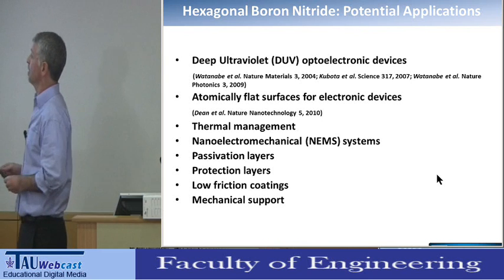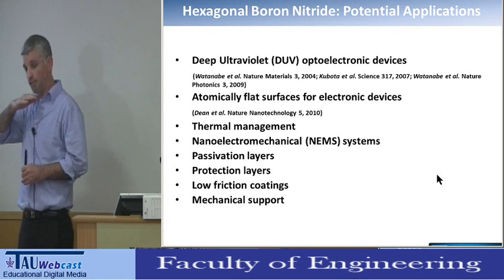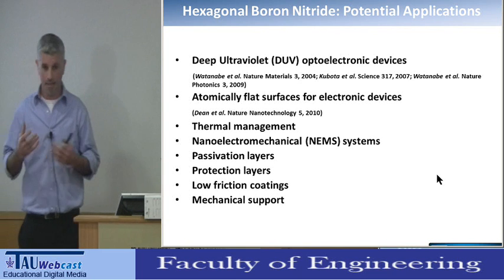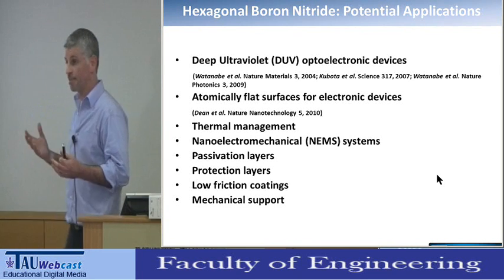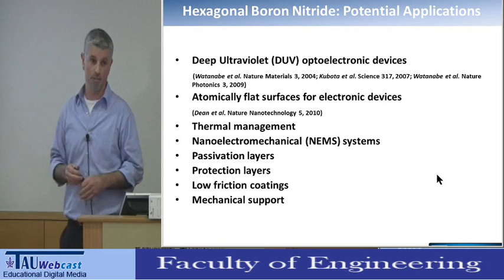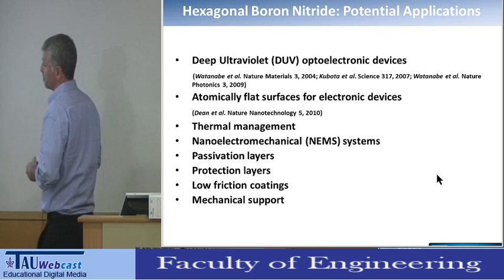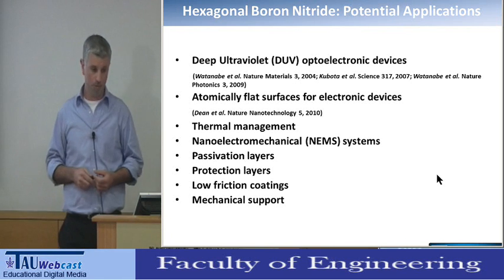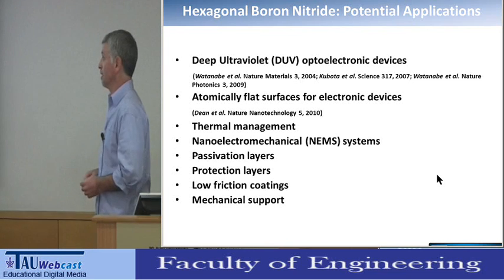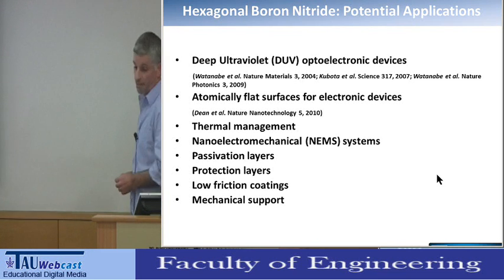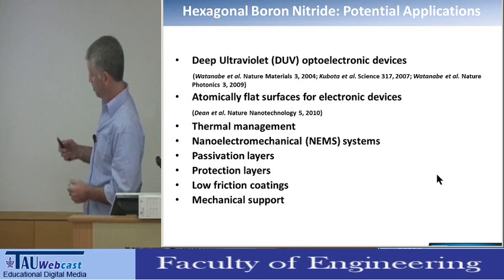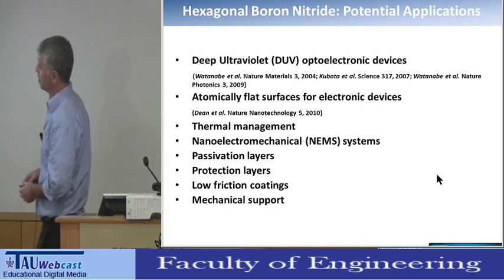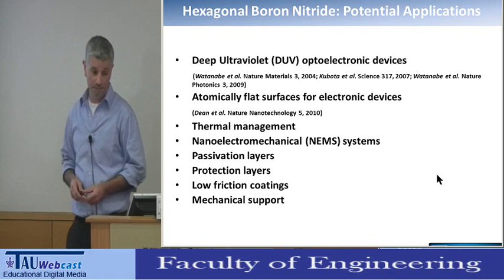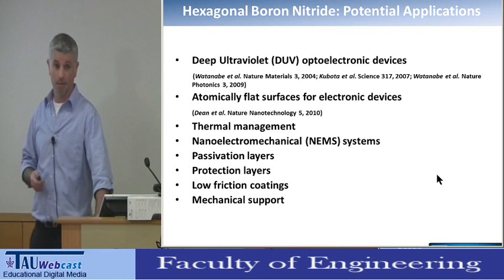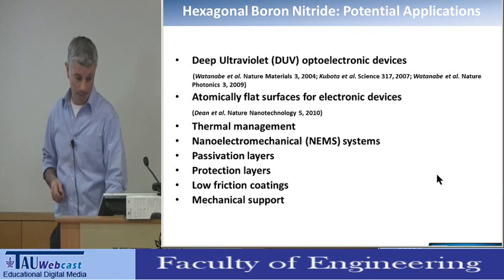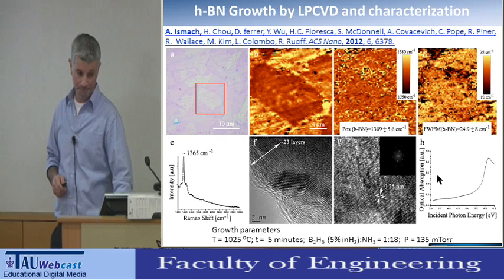And the reason for that is, again, that the hexagonal boron nitride is atomically flat. It doesn't have any dangling bonds. It doesn't have any surface states that can scatter the charges in the graphene. And in principle, it's also a very good thermal conductor, which is also a good thing to have in electronic devices. It was shown also that it is a good material for deep UV optoelectronic devices, and again, it's a very good thermal conductor, so it can be used for thermal management applications.